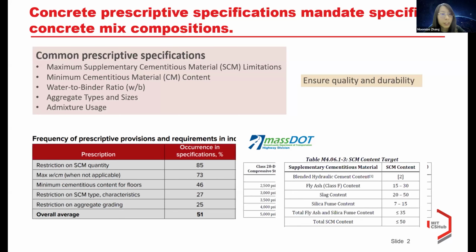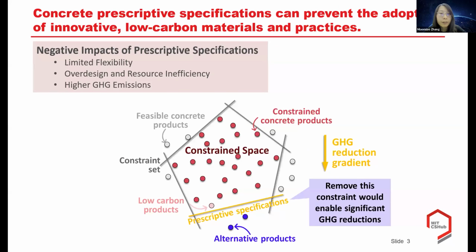However, they may have some limitations or negative impacts. First, they impose constraints on concrete mixtures and limit the flexibility in concrete production. For example, requiring a minimum cementitious material mass can lead to overdesign and resource inefficiency, as Soroush explained. Additionally, prescriptive specifications often restrict the use of low-carbon materials like fly ash and slag and lead to higher GHG emissions. For example, in this figure, if we remove these prescriptive specifications, it would enable significant GHG reductions, and we can find alternative products instead of the low-carbon products within the constrained space.